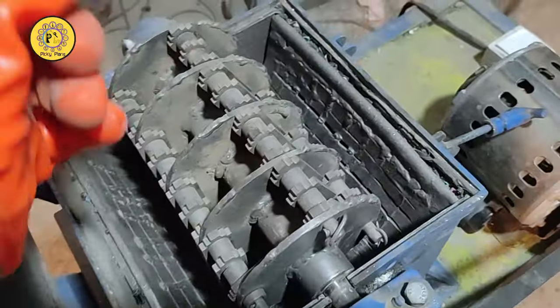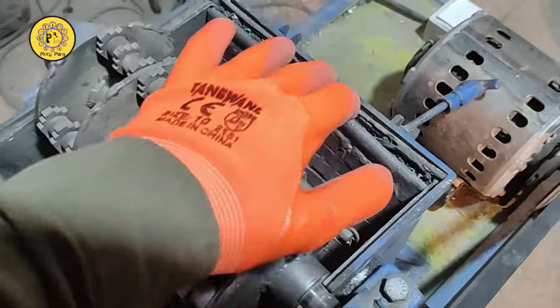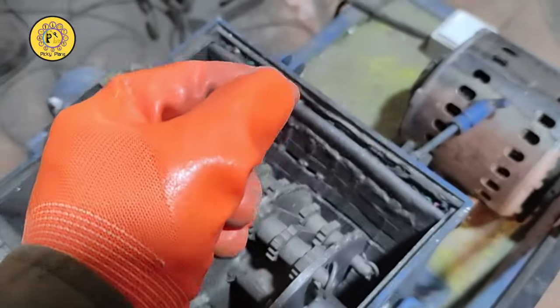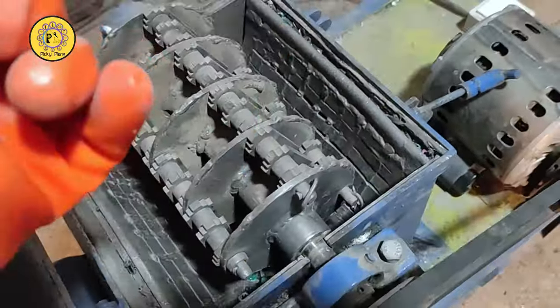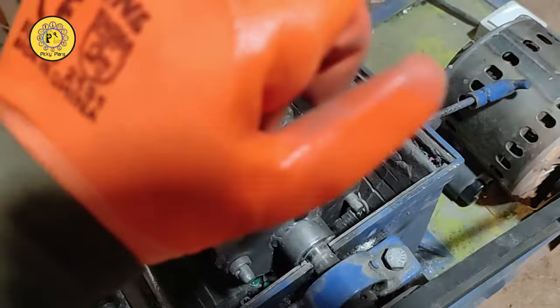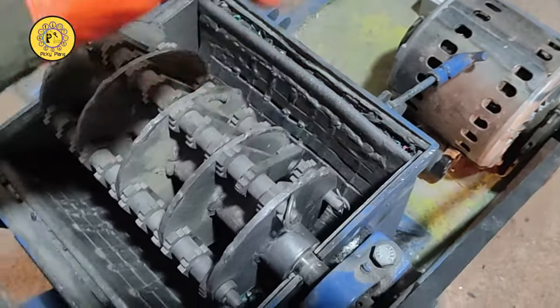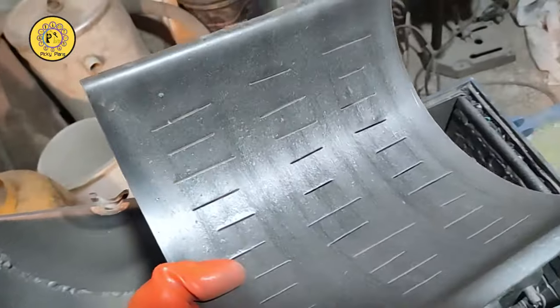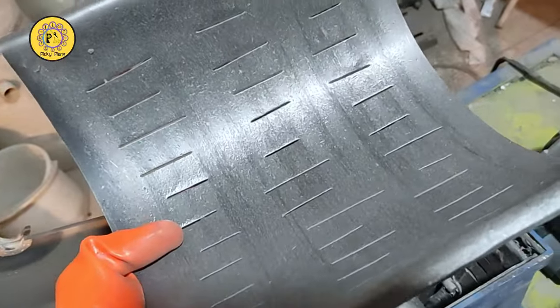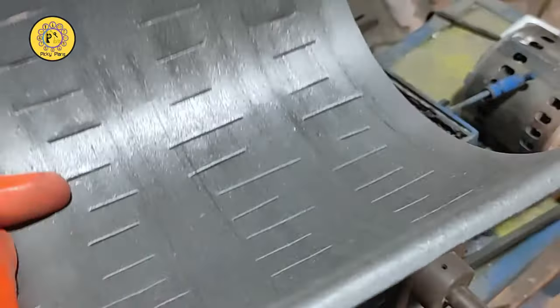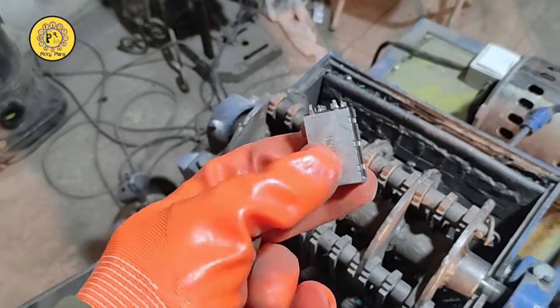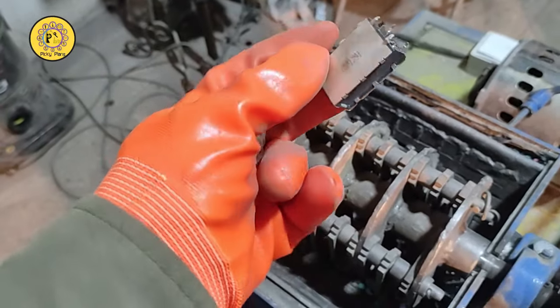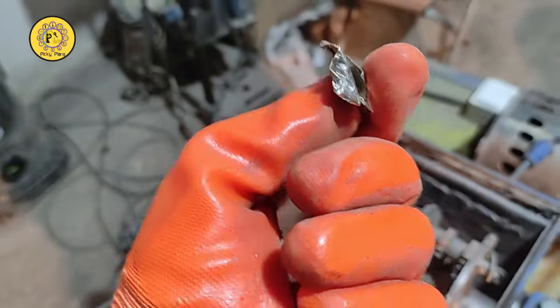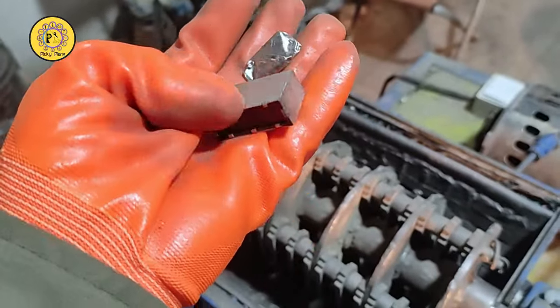I want to minimize the friction between the materials inside this hammer mill, for the pins not to lose any gold, or at least minimize the gold plating being peeled off by the action of the hammers. And this is a screen with a smaller diameter, which I decided not to use. First, I'm going to start with grinding these parts to tear off the steel part and release the pin materials inside.